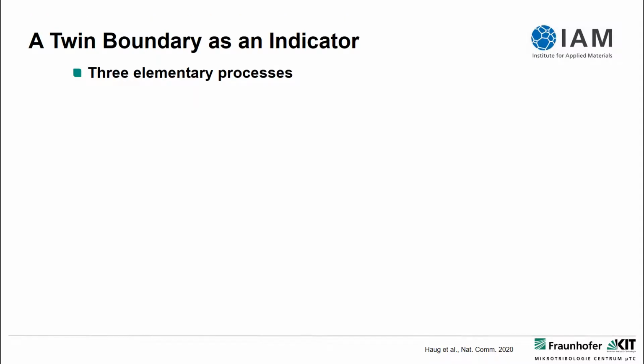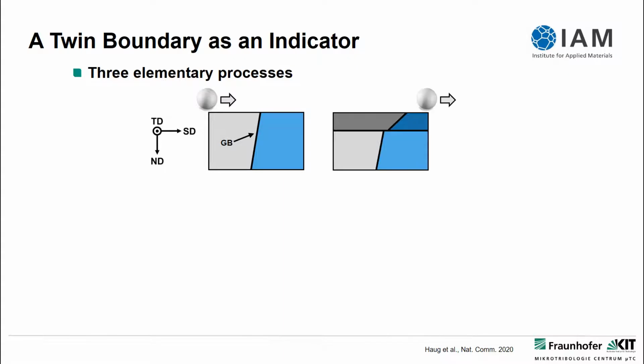So what we can infer from this TEM foil, in our opinion, are three elementary processes. The first one is this tilt of the twin boundary, so there is a crystal rotation accommodated in the transverse direction by the dislocation trace line. After the sliding, that's exactly what we see here: we have the dislocation trace line, and the material above it is rotated around an axis going perpendicular to the screen, in sliding direction.